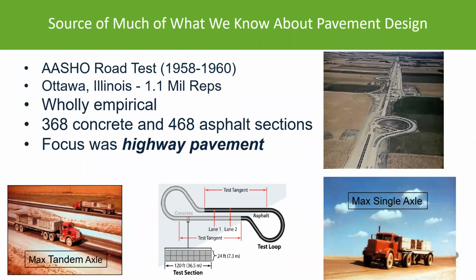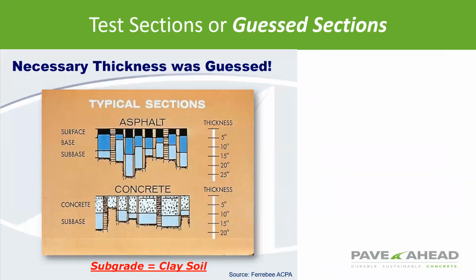And it says here that what they did there was look at what the pavement did based on the traffic that was driving on those 368 concrete pavement sections and 468 asphalt pavement sections. This was purely for highway pavement. Up with those test sections, well, they guessed asphalt and concrete. Here are some of the typical sections with asphalt and concrete.